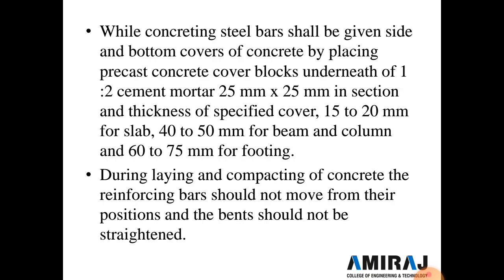Now while concreting, steel bars shall be given side and bottom cover of concrete by placing precast concrete cover blocks underneath, of 1:2 cement mortar, of 25 by 25 mm in section, and the thickness of the specified cover is 15 to 20 mm for a slab, 40 to 50 mm for a beam, and 60 to 75 mm for a footing. During the laying and compacting of the concrete, reinforcing bars should not move from their position, and bends should not be straightened.